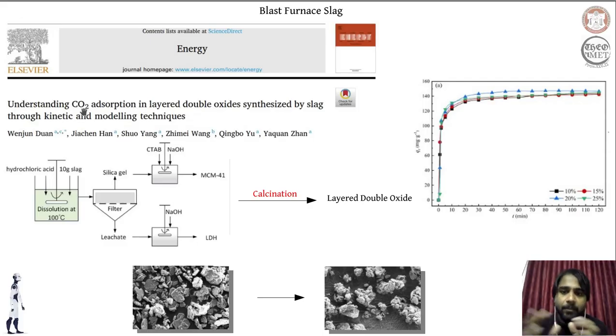And as you can see, one advantage of having the layered double oxide in place of layered double hydroxide is that irrespective of the amount of LDO being deployed for a given purpose of absorbing CO2, the efficiency more or less remains the same. Here, as you can see, different percentages of LDO are deployed in the filters for carbon dioxide adsorption, and the performance more or less remains the same. So ultimately we are achieving a greater absorption with a lesser amount of this kind of material. So when we change from LDH to LDO, the efficiency increases, and that is the reason why this additional step is taken.